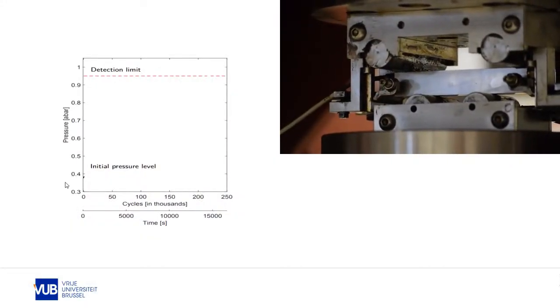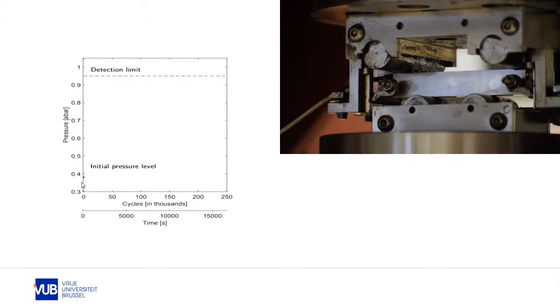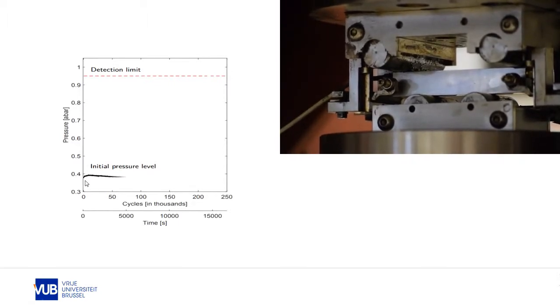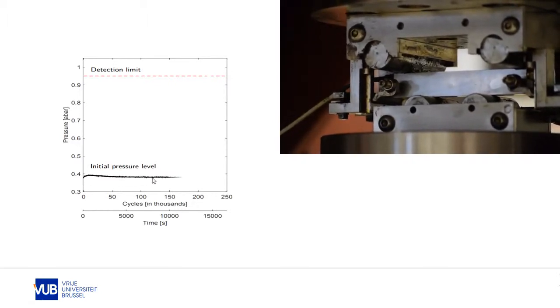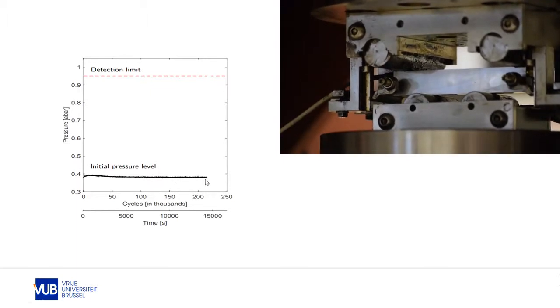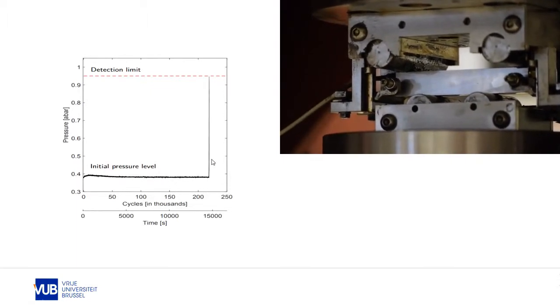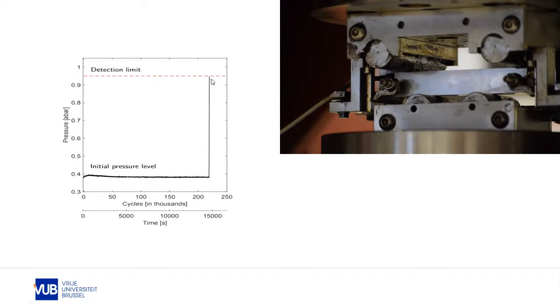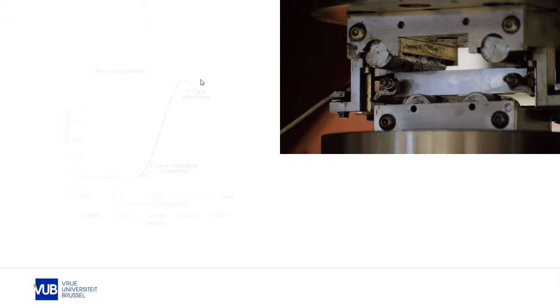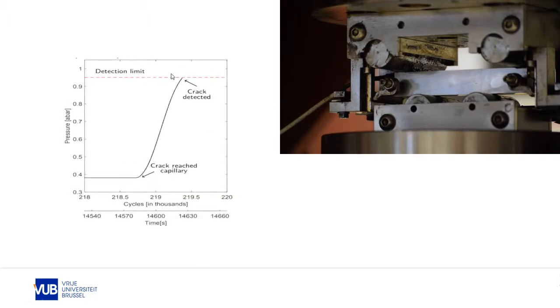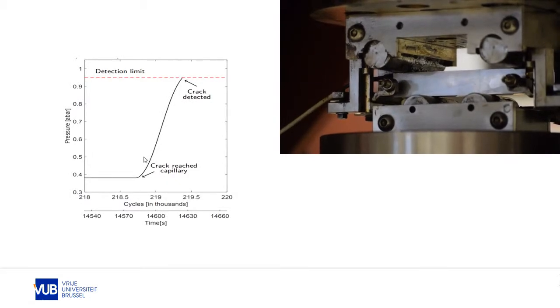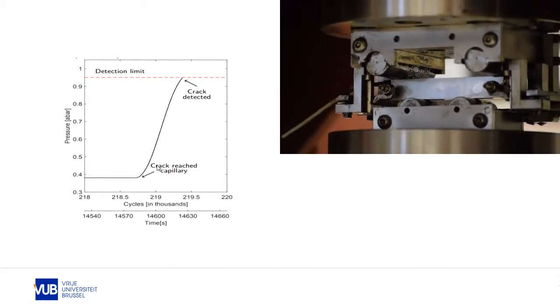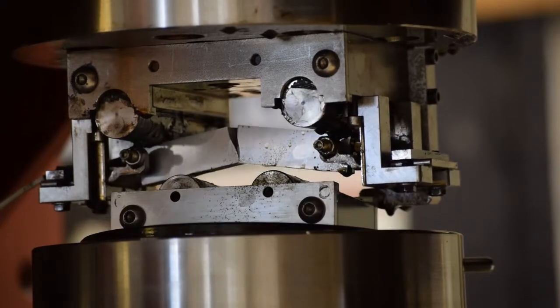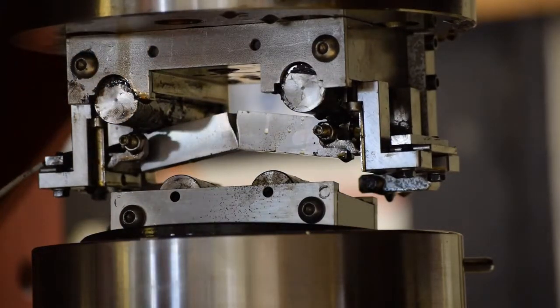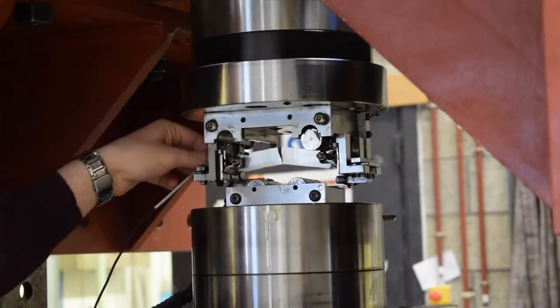At the start of the fatigue test, the pressure remains constant at the initial pressure level. However, when a fatigue crack is present, the pressure starts rising. The fatigue crack is detected and the fatigue test is stopped when the pressure inside the capillary surpasses a preset limit. The steepness of the pressure rise depends on the size of the fatigue crack. Besides the actual detection of the damage, the ESHM system also provides the investigator with an indication of the size of the crack.